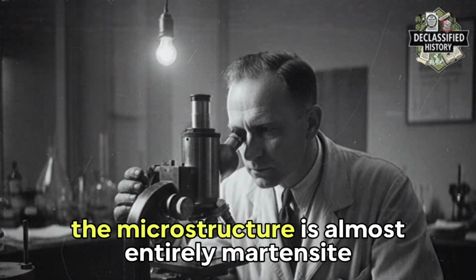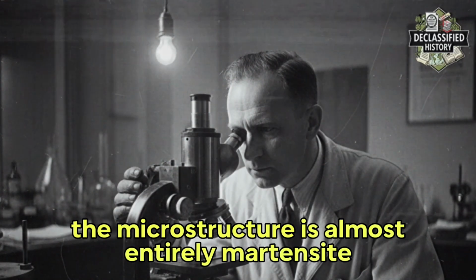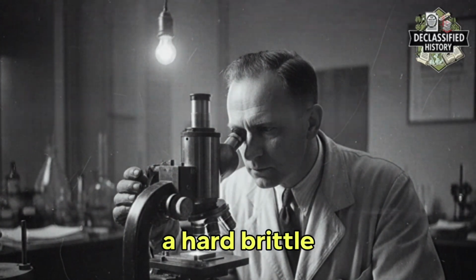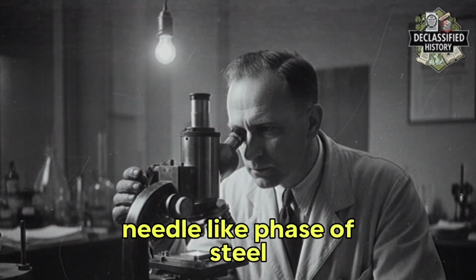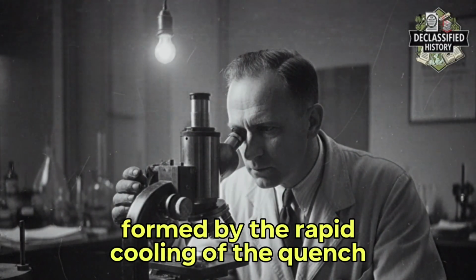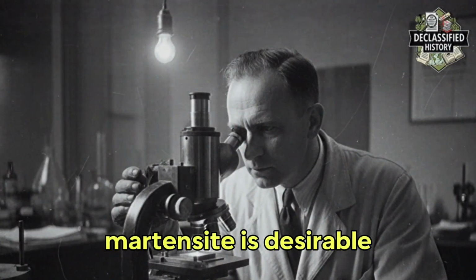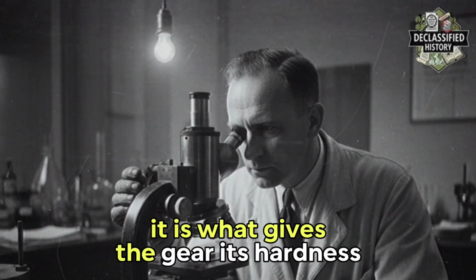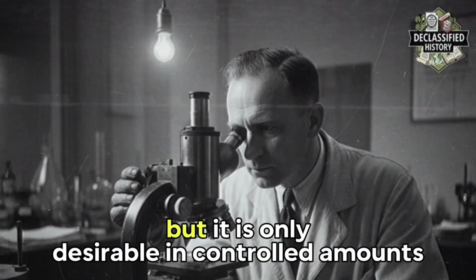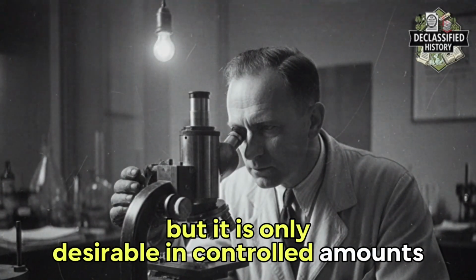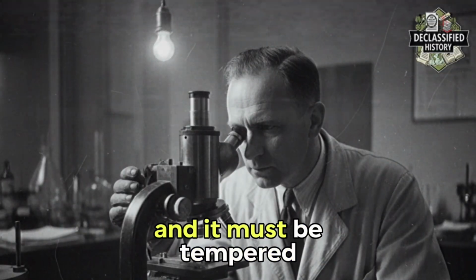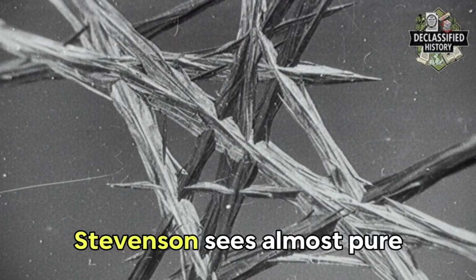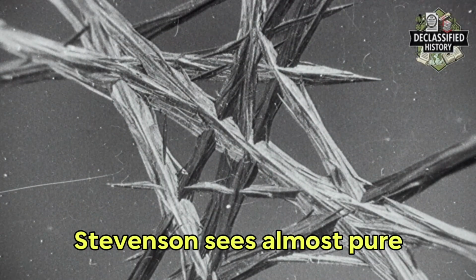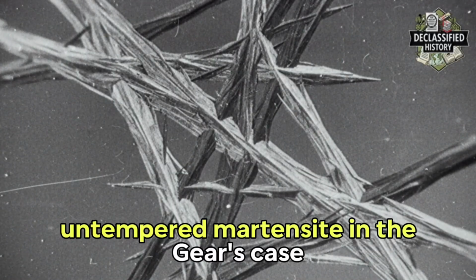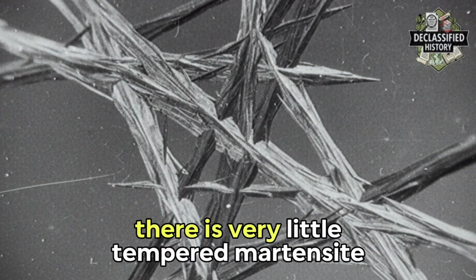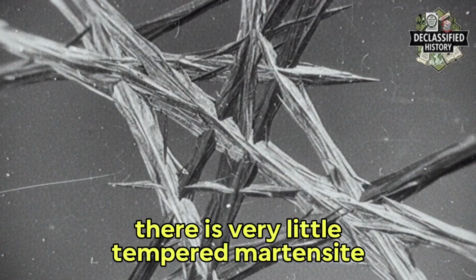The microstructure is almost entirely martensite, a hard, brittle, needle-like phase of steel formed by the rapid cooling of the quench. Martensite is desirable. It is what gives the gear its hardness. But it is only desirable in controlled amounts, and it must be tempered. Stevenson sees almost pure, untempered martensite in the gear's case. There is very little tempered martensite.